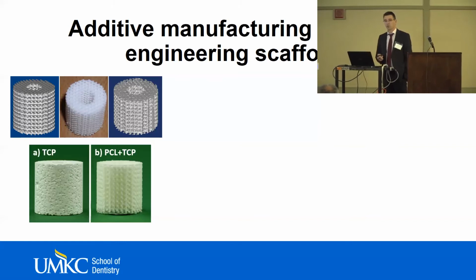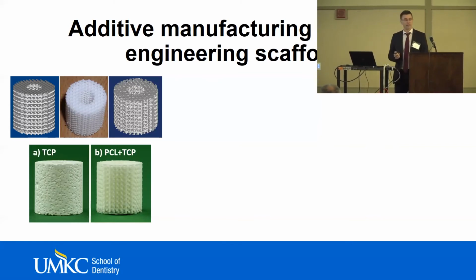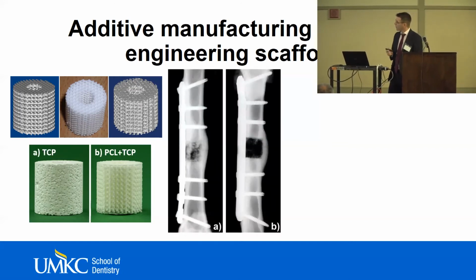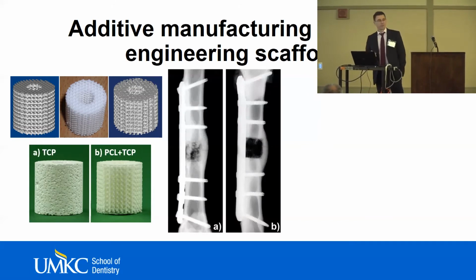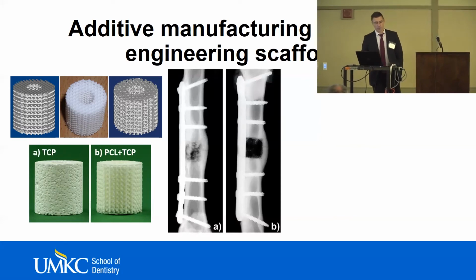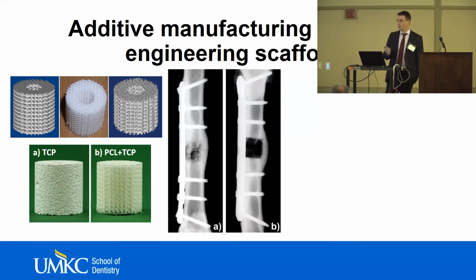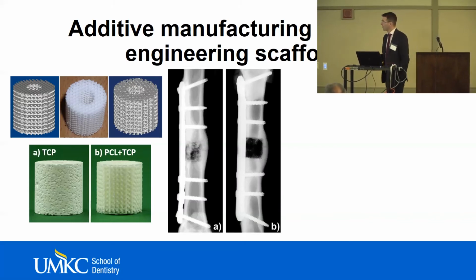So these two scaffolds were implanted into sheep tibia and left in there for up to 14 weeks. After excising them, we saw results like this, and you would suggest from these pictures that the TCP scaffold is still significantly more successful than the polymer scaffold we used. Now, as you probably know, in X-rays, calcium phosphate shows up almost similar to bone because of the similar density. So from these pictures alone, we cannot tell if we actually had bone ingrowth into our TCP scaffold, while for the polymer scaffold on the right side, it just looks like a void. But that's just due to the low density of the polymer, so it doesn't show up.